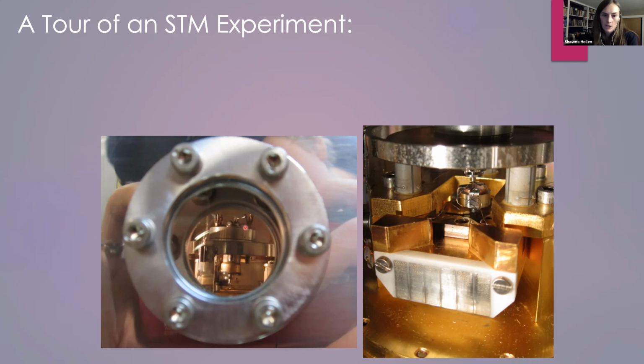So first of all, the STM is inside this tiny little window tucked away in an ultra high vacuum chamber. So the vacuum in this chamber is better than outer space, actually. And the temperature is pretty low, pretty comparable. This one was at 5 Kelvin. So that's 5 degrees above absolute 0. So your STM is tucked away in this ultra high vacuum, low temperature environment. And it's also hanging from springs to reduce or eliminate vibrations.